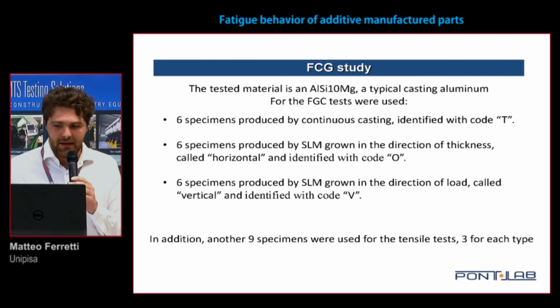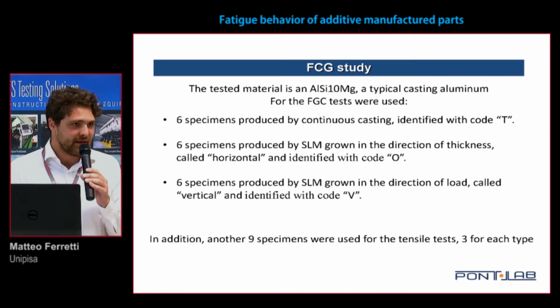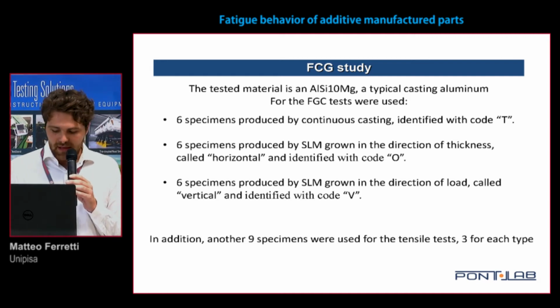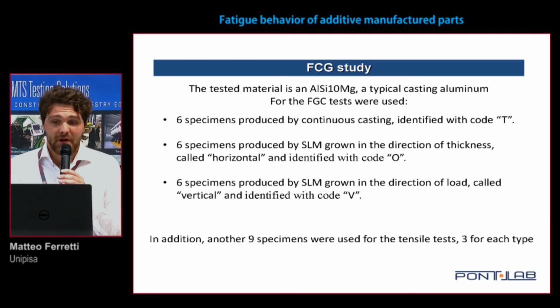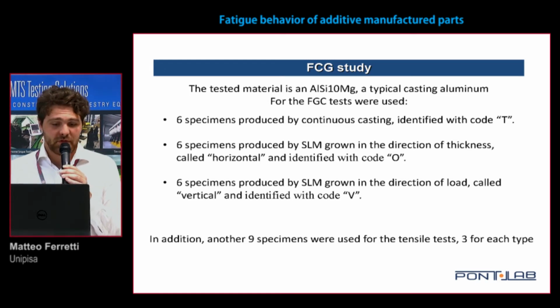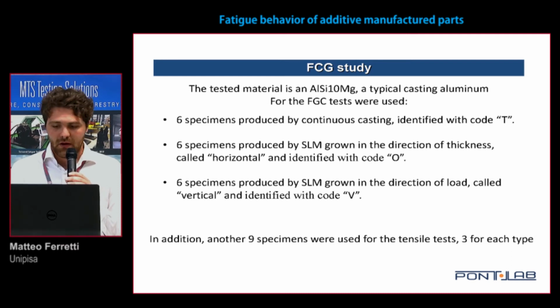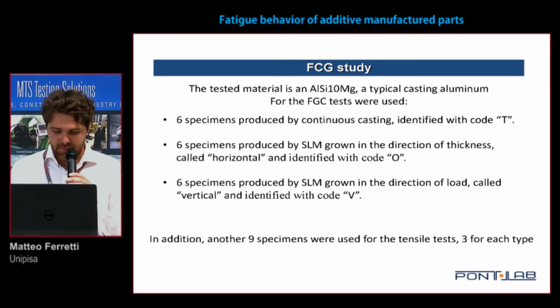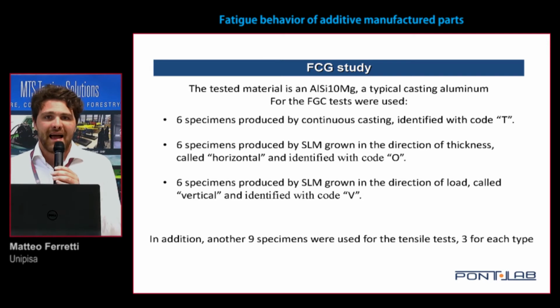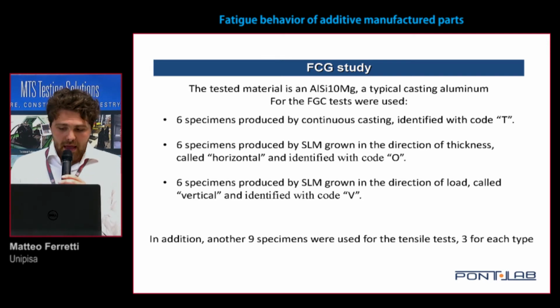The tested material is AlSi10Mg, that is a typical casting aluminum. And for this study, we used 6 specimens produced by continuous casting, identified with the code T, 6 specimens produced by selective laser melting, grown in the direction of thickness, colored horizontal and identified with the code O, and 6 specimens produced by selective laser melting, going in the direction of the load, colored vertical, identified with the code V. In addition, another 9 specimens were used for the tensile test, 3 for each type.